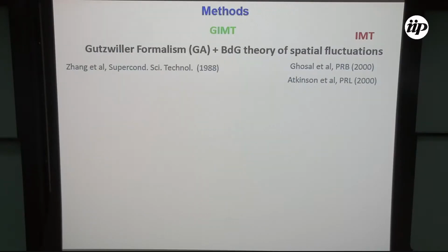So how to solve it? We wanted to take care of the inhomogeneities in the sample. So we did a Bogoliubov-de Gennes theory in real space, because we have disorder, which I will call inhomogeneous mean field theory. And to incorporate the strong correlation, we have done a Gutzwiller approximation, and I will call this method with both Gutzwiller approximation and BdG theory in real space GIMT, which is Gutzwiller inhomogeneous mean field theory. So I would use these acronyms later.